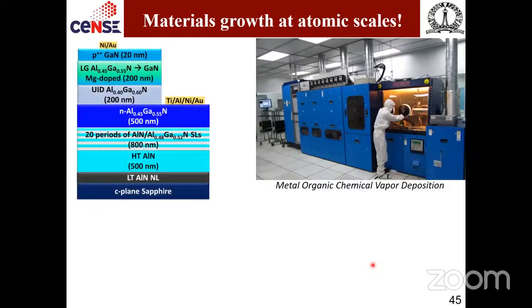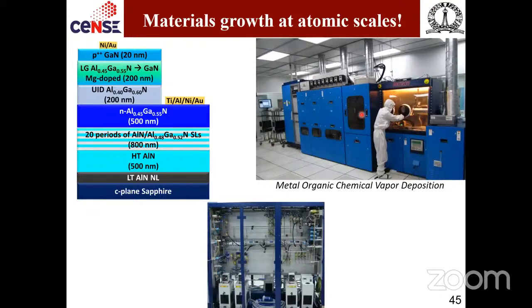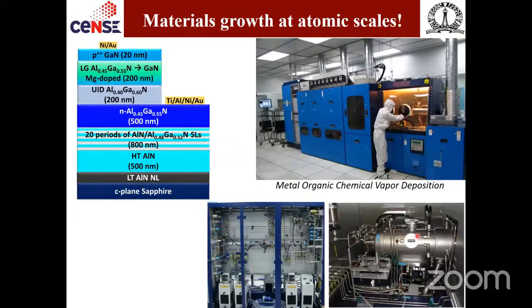So this really enables us to grow complex structures like the ones shown here. Although the film thicknesses are only nanometers in size, you still need such a large reactor to control the deposition. If you open one of these gas cabinets, you see a trail of lines. These are gas lines through which we pump the precursors and make them react. So this is the main reactor.